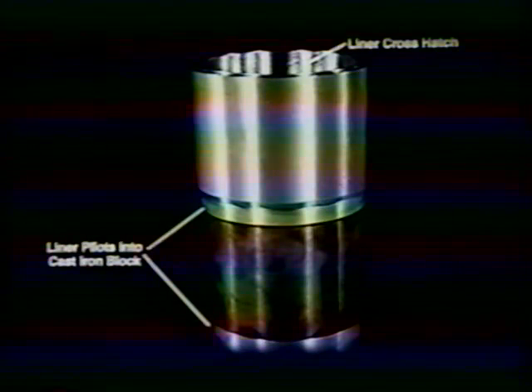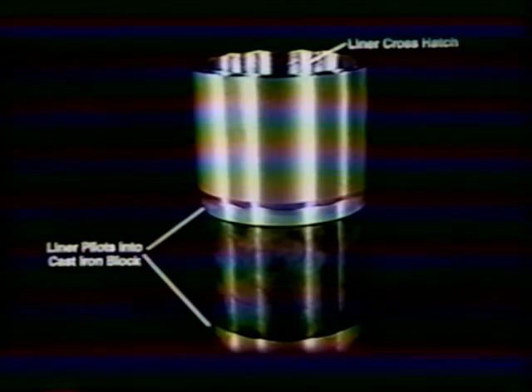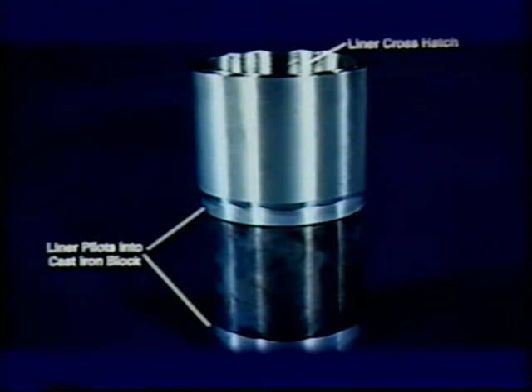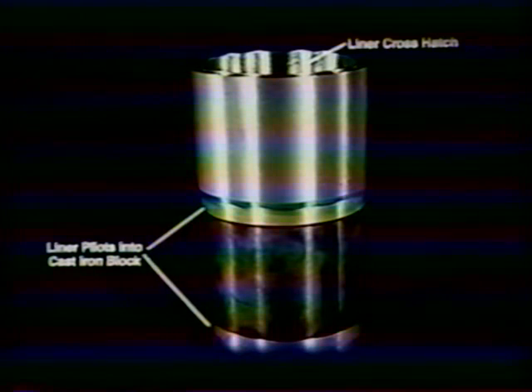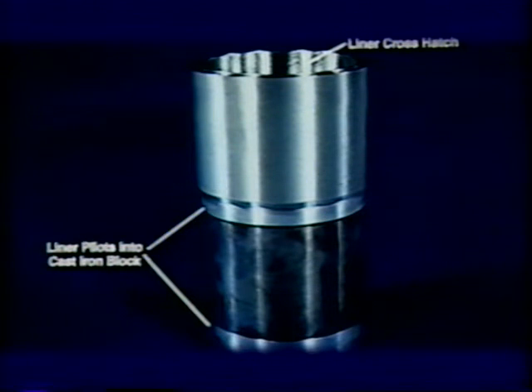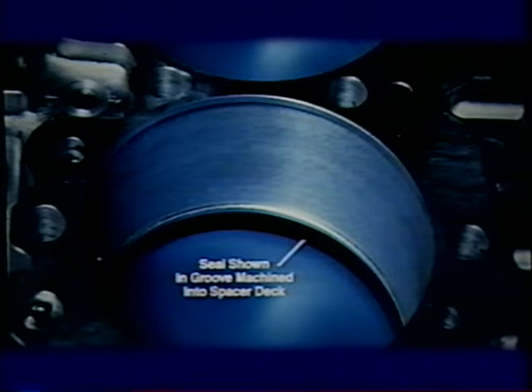The cylinder liner is a mid-support design seated on the top face of the iron block and piloted below the seat and at the bottom of the block. The liner is cast iron and the bore is induction hardened for additional life. A precision honing process yields superior cross-hatching for excellent oil control. Liner sealing is above the seating surface with a rectangular seal placed into a groove machined into the aluminum spacer deck.